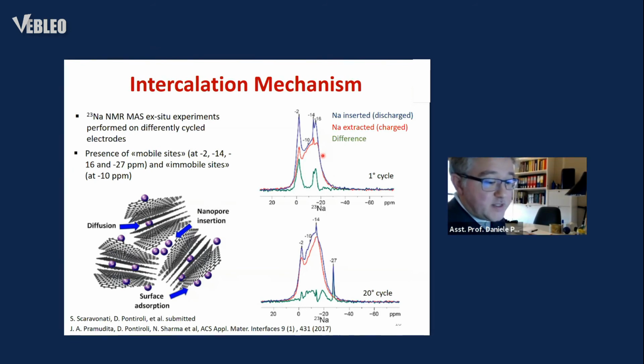Further electrochemical characterizations, such as impedance spectroscopy and 3-electrode cyclic voltammetry, allowed us to better clarify the presence of two intercalation mechanisms for mobile lithium and sodium in graphene. A battery-like electrochemical intercalation due to lithium insertion between graphene layers and responsible for the large capacity of graphene, and an electrostatic accumulation of charges due to lithium adsorbed into the graphene pores or attracted by electrical charges on the graphene surface, responsible for fast charge and discharge capabilities.